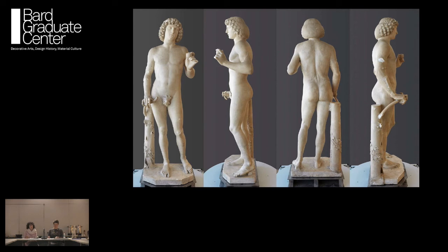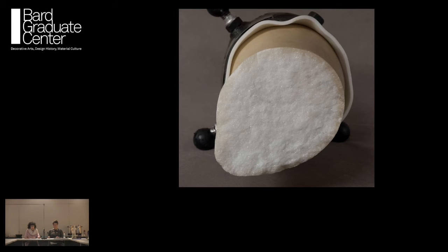During the sculpture's history, animal fat was applied to the surface, both to impart gloss to the surface and as a means, so it was believed, of mitigating salt contamination. This technique was typical for marbles of Italy. The fats applied to the surface sank into the marble, darkening and yellowing over time. You can see in this section of Adam's leg just how deeply the fats penetrated the surface. There's a distinct yellowish ring around the circumference, which in places measures up to a quarter inch wide.